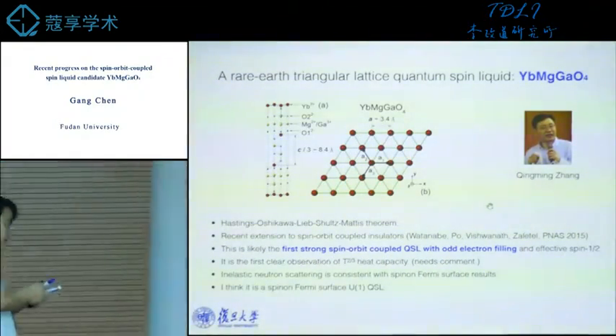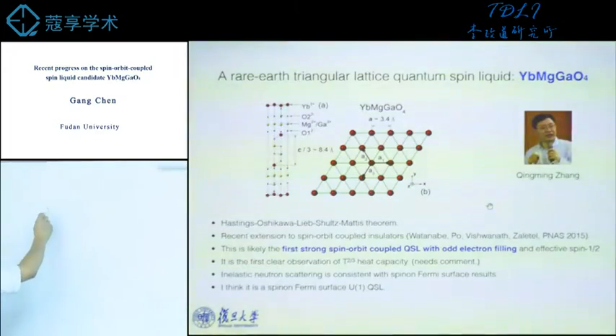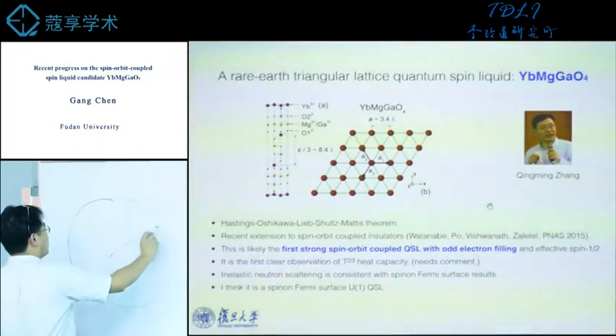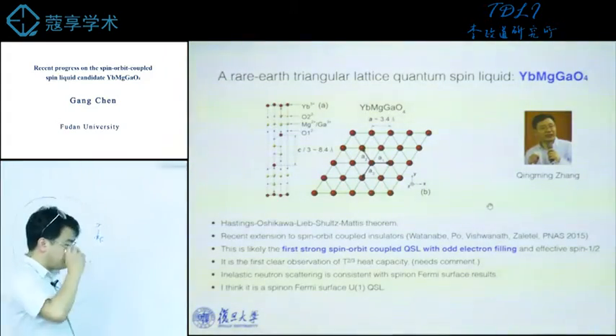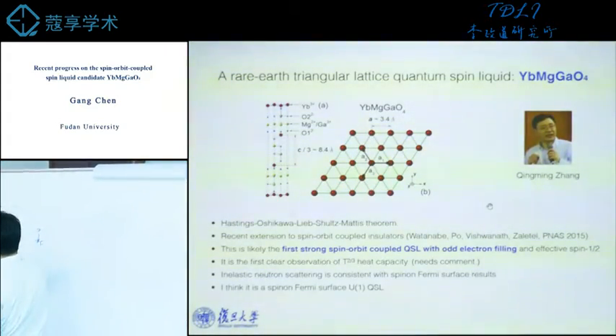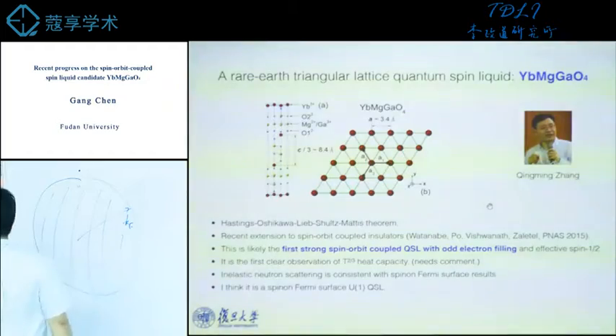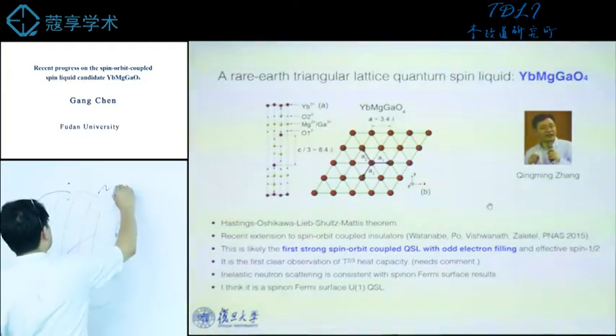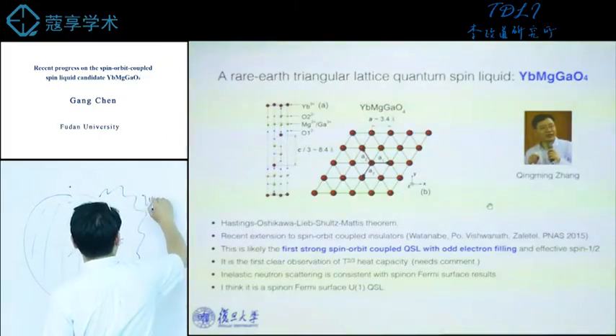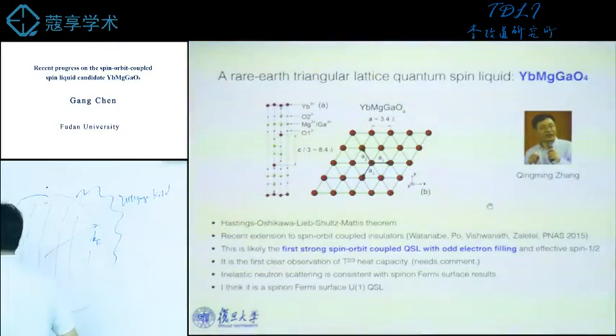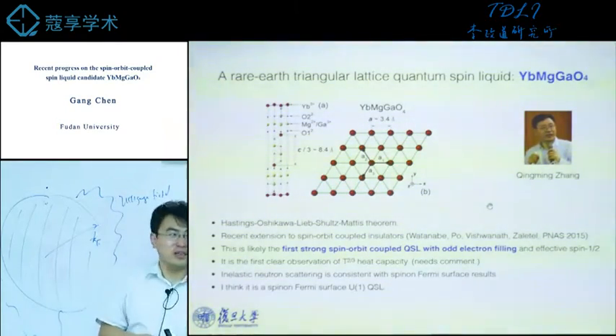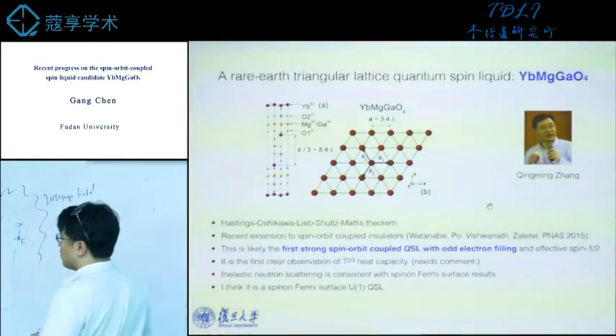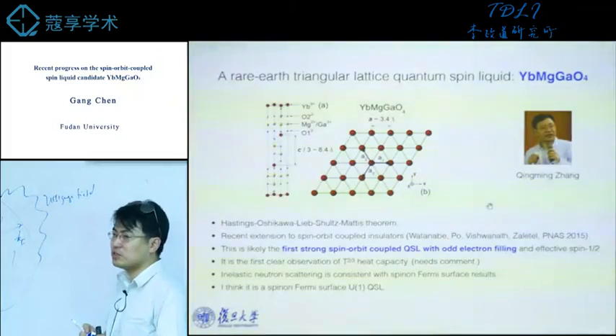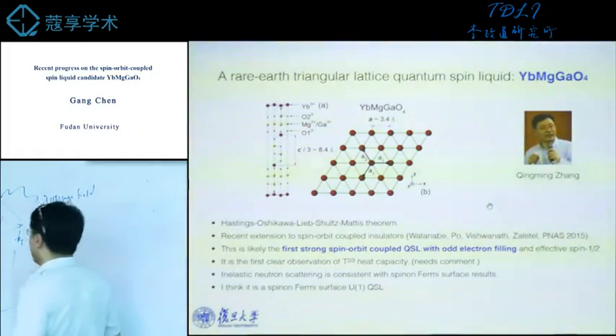Okay, turn to this whiteboard. So the story is there is a spinon Fermi surface with a momentum kF. This is the Fermi momentum kF. So this is completely filled with spinons. So the low energy excitations are spinon particle-hole pairs, right? But these are coupled with the emergent U(1) gauge field. This is a strong coupling theory. This coupling is not weak. It's of order 1. It's not like quantum electrodynamics, where the coupling is small due to the very weak fine structure constant. The fine structure constant is very small, so you can do a perturbative expansion. This is not.